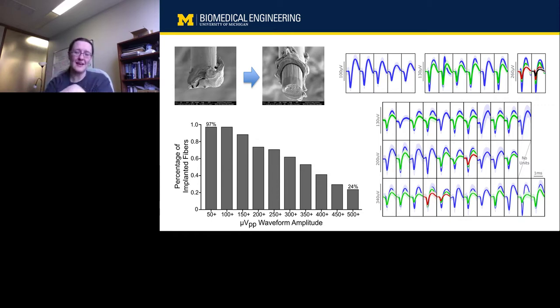So I'm showing you acute data, and you can see our new chronic data in our upcoming paper. But looking at 97% of the electrodes recorded a spike that was greater than 100 microvolts, and a full 24% of our electrodes recorded a spike that was 500 microvolts or more. So again, the existing arrays that we've been using are pretty good. We still use the Utah array for all brain-machine interface experiments in my lab. But I think it is fair to say that we would be recording a lot more neurons if we didn't have some of the scarring problems that were associated with conventional probes. And we really want to see this kind of yield on one day a human device.